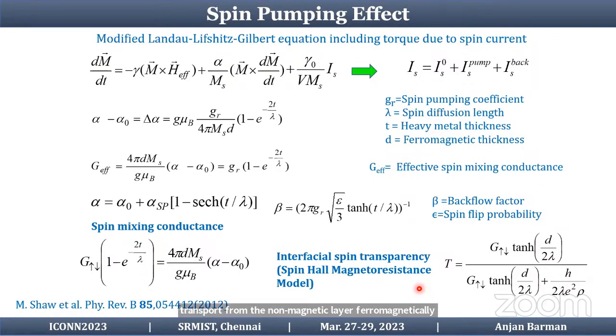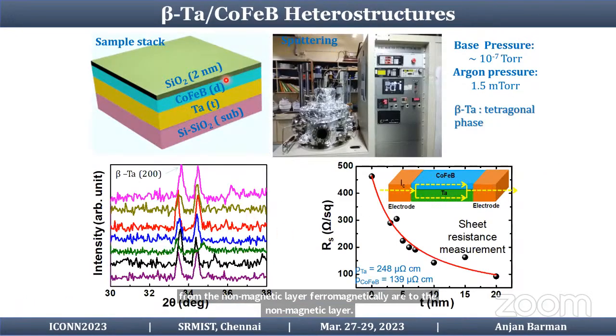The spin transparency governs the amount of spin current transported from the ferromagnetic layer to the non-magnetic layer. So we did this experiment on a cobalt iron boron tantalum system, which was grown in our lab using a sputtering unit, and we confirmed the beta tantalum phase in this sample. We measured the sheet resistance, from which we found the tantalum and cobalt iron boron resistivity.